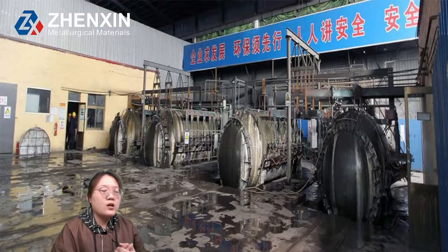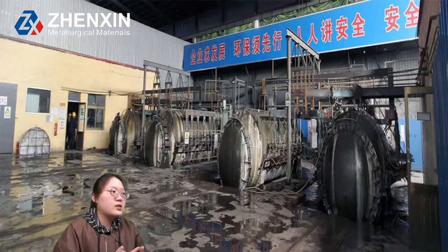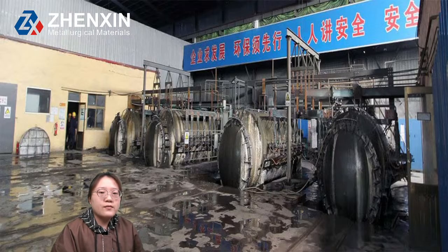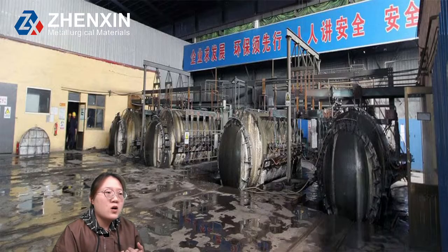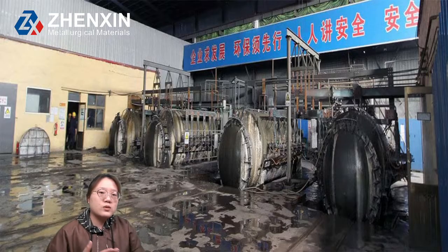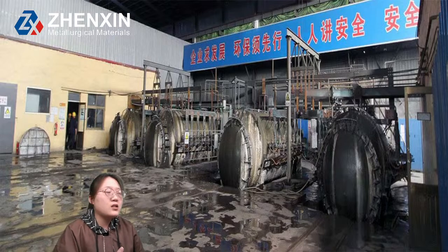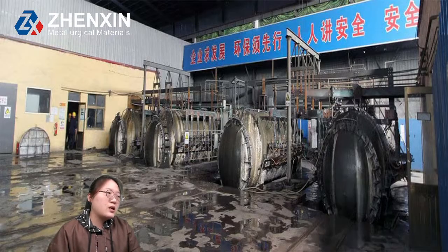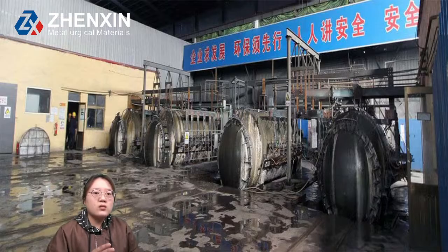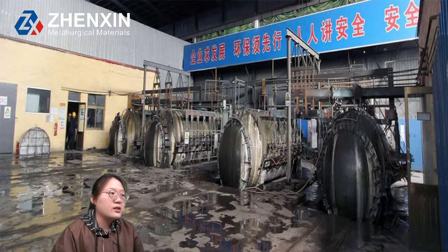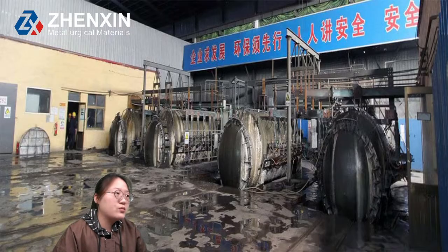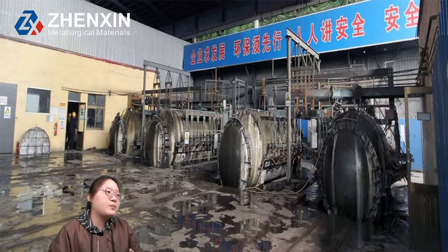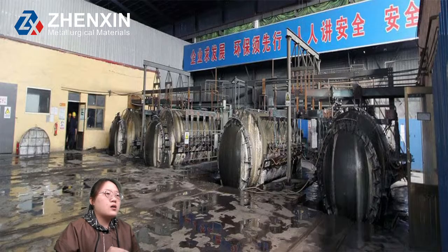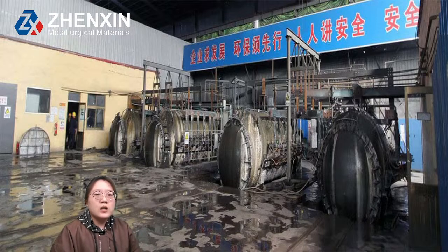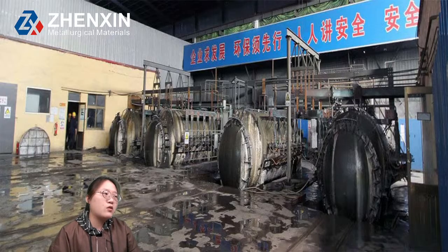For the ferrosilicon magnesium, the specification for reference is as follows: the silicon content is higher than 44%, the magnesium content is between 7 to 9%, the calcium is between 1 to 3%, and the rare earth element is about 2 to 4%.